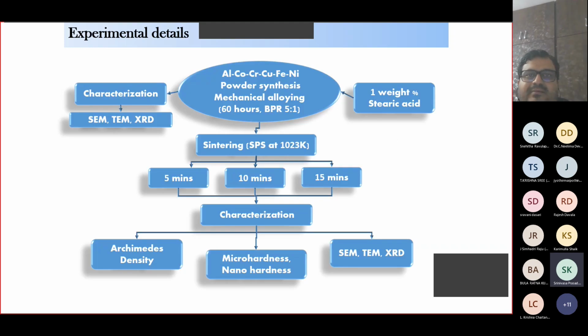And these materials again, the example that I'm showing here is aluminum, cobalt, chromium, copper, iron, nickel, and all are taken in equal proportions. Therefore, you cannot call this an aluminum alloy, you cannot call this a cobalt alloy, you cannot call this a chromium alloy, you cannot call this a copper, iron, or nickel alloy, because all are in equal proportion. That's why you just call them multi-principal element alloys.